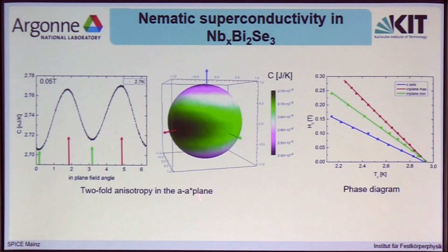And while you see, of course, a clear in-plane to out-of-plane anisotropy, you also clearly see a twofold anisotropy in the plane, with this dark shaded region here and this light green region there for the two 90-degree different axes in the plane. Also here, you can see it if you extract the phase boundary. There's a maximum and a minimum in-plane upper critical field.